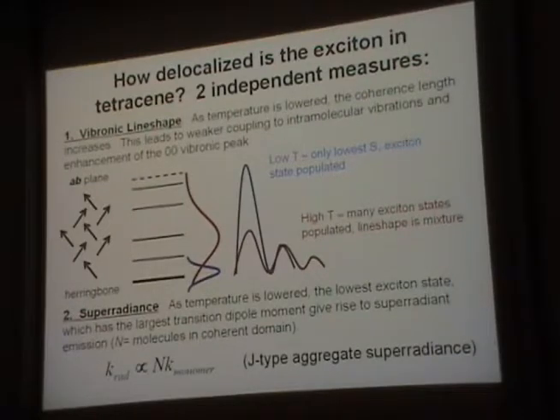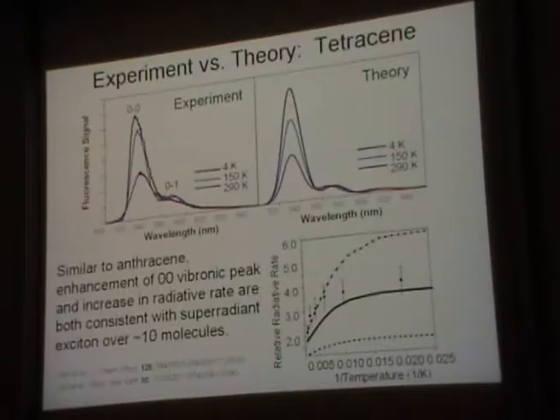That's called superradiance, okay? So superradiance is where you get this big enhancement in your oscillator strength because all the molecules are working together. They're working together to ignore the vibrations. That's why your 0-0 peak goes up. And they're working together to concentrate all the oscillator strength into that transition, that low energy transition. So those are the predictions that you would get from this type of theory. And those are the experimental results that you get, okay?